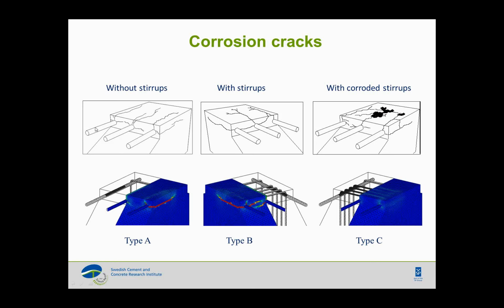We look at some of the crack patterns. On the top we have the crack pattern sketch from the test in the lab. So here is the specimen type A without any stirrups, where we actually have a more local crack pattern. In this case we have corner covers falling. That's what we also see in the simulations. In type B, where we have stirrups included, cracks tend to end up with cover delamination. So one crack here, and then that propagates to the middle bar and so on. And that's what we also see in the simulations.